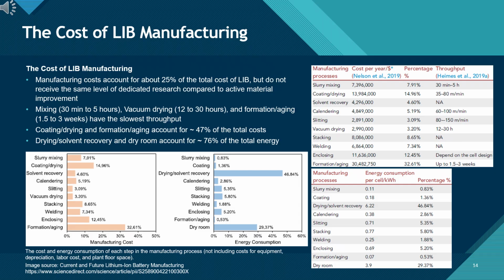From a cost distribution perspective, the two dominant contributors are coating and drying, and formation and aging, which together account for nearly half, about 47%, of total manufacturing costs. Energy consumption shows an even sharper concentration. Drying/solvent recovery and maintaining the dry room environment alone make up about 76% of total energy use. These areas are therefore major targets for cost reduction strategies such as solvent-free coating, more efficient dryers, or advanced dry room systems. The accompanying charts clearly illustrate these contributions.